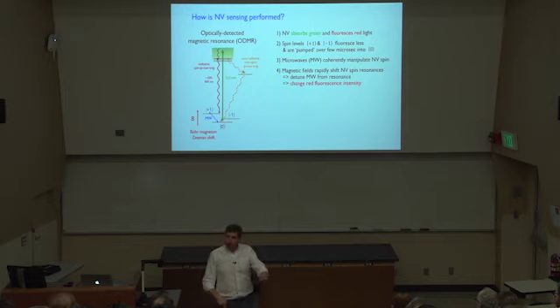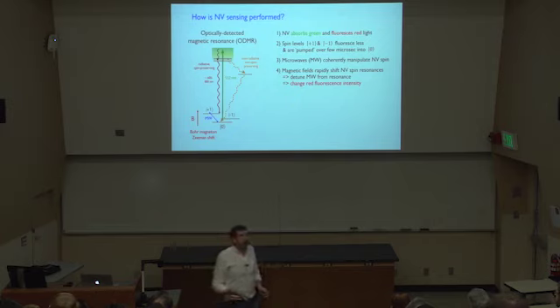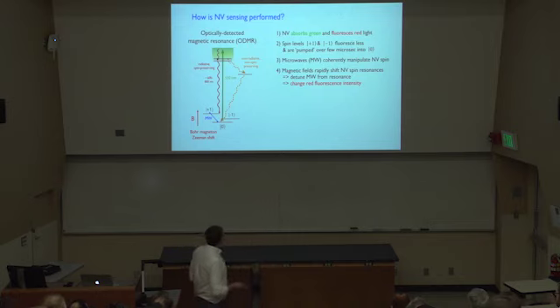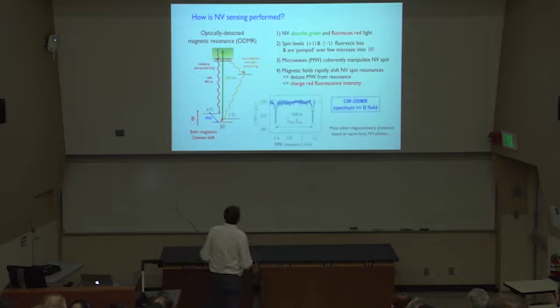And over a longer time, as you get out to a microsecond or so, no matter what state you started in, you're going to end up in ms equals 0. So that's your initialization step. Hit with the green light, wait a microsecond or two, you're in ms equals 0, and you've prepared your spin state. After that, the difference in the fluorescence rates, depending upon the experimental protocol, will give you information about the magnetic fields that the system has been exposed to.